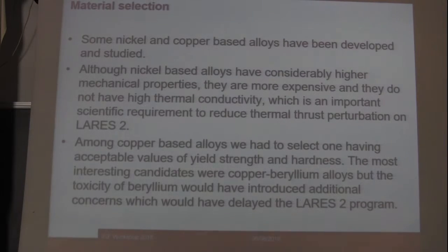So, as far as the material selection is concerned, after many studies, we selected some nickel and copper-based alloys that have been developed and studied. The first candidates were nickel alloys that have higher mechanical properties, but on the other hand, they are more expensive, and they have a low thermal conductivity. Why do we need a high thermal conductivity? Because we need to reduce perturbations on LARES-2.